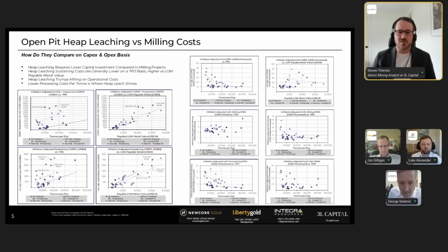On sustaining costs, heap leach generally requires lower sustaining capex than milling. However, when you look at it against the life of mine payable metal value, it can sometimes be more expensive. For open pit milling operations, variability comes from factors like ore hardness or tailings dam phasing. For heap leach, the sustaining capex, a lot of it's going to be for expanding the leach pads. And it can actually be quite lumpy as you expand the pad every so often to increase the capacity and be able to stack more tons.